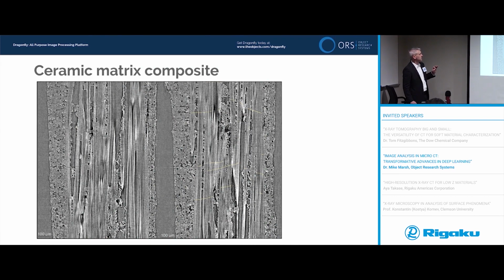Now, this is interesting. I suspect maybe no one in the room is close enough to see the breaks, but they actually took the composite inside the micro CT, and it was under a tension cell with acoustics hooked up, ultrasound transducers hooked up, and they pulled on it until they heard cracking, and they knew that the composite was cracking. And there's, I can't even see it. There's a crack here, and there's a crack here, and there's a crack here and here.